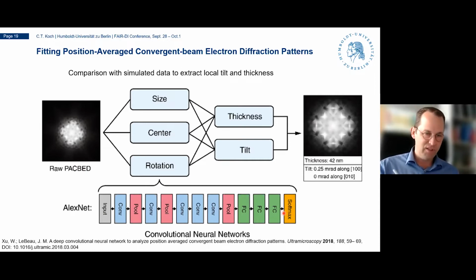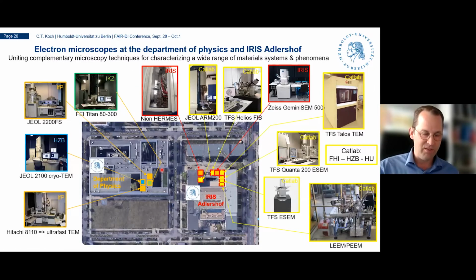But if you do this for the same experiment, for the same microscope, you can easily do this because you have calibrated your camera lengths of the diffraction patterns and so on, and also the way that your detector works. But if you try to apply this now to data provided by other groups, it becomes more complicated because the detector characteristics play a role. Maybe the calibration of your camera length needs to be redone and so on. There are many complications, and I will deal with that right now.